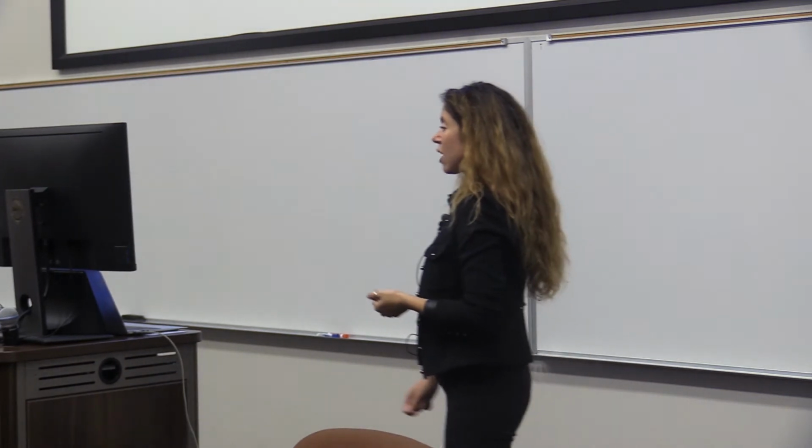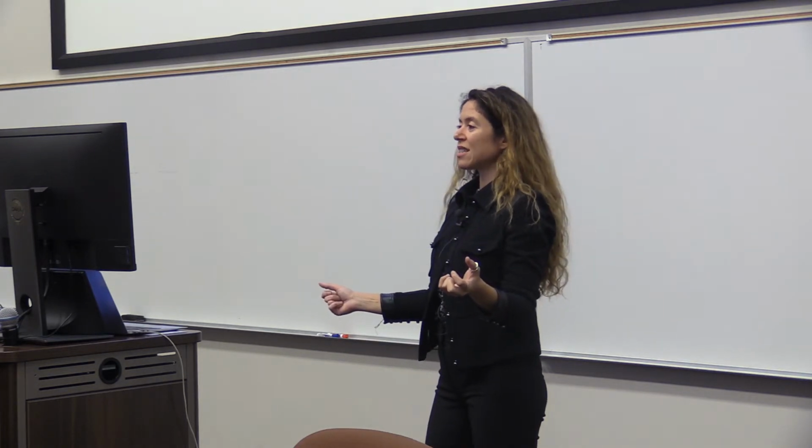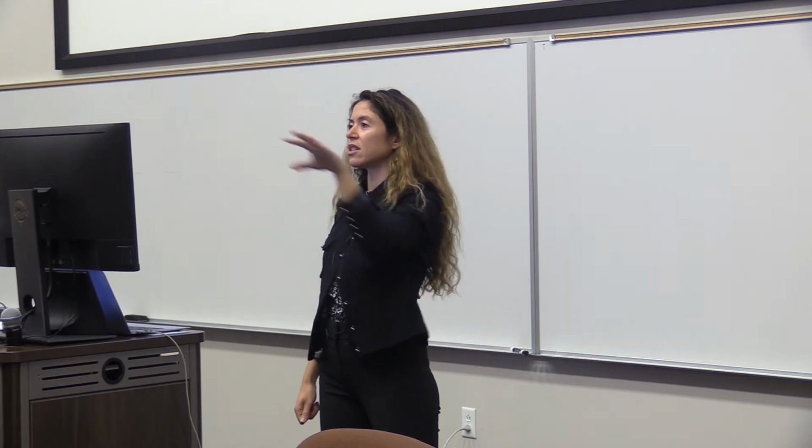Okay, so now let's measure the average linking number in this system. Okay, let's go to the first one. Well, if I do average linking number here, I have to count all pairs of linking numbers, right? So I will take linking number of that with that, linking number of this with this, of this with that, of this with any other image. So we are talking about an infinitely many pairs, right? But you might say some things are so obviously not linked, the linking number of those will be exactly 0. That is true. So actually, that can be a finite sum. I can get a grain of only finite information that is repeated throughout.